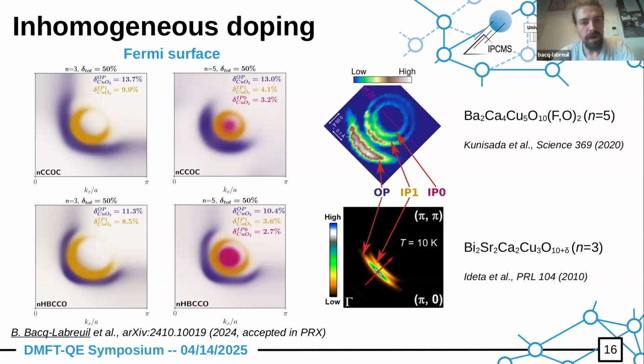Of course, this is beautiful, but it's better if you can compare to experiments. So this is a comparison to experiments. Below, you have a tri-layer compound, bismuth-based superconductors, measured in ARPES in this work of Ideta and collaborators, where you nicely see these two arcs of different size. Then you have the 5-layer compound measurements of Kunisada and collaborators from 2020, where you really see this coexistence of two pockets and an outer arc. This, we believe, tells us that we are probably doing the right thing.